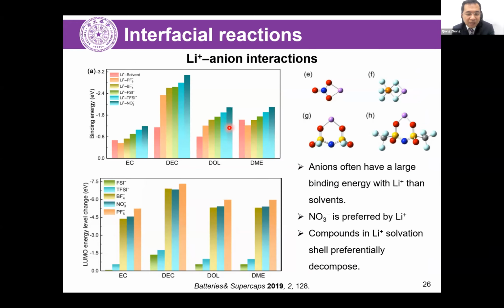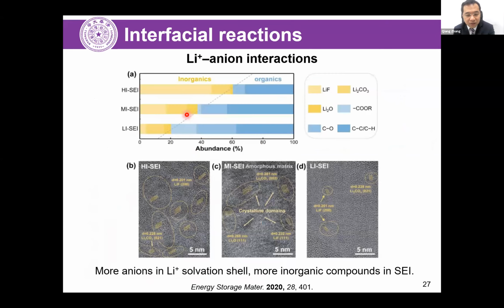So in this case, we use ab initio calculation to probe the bonding energy. And it is found that the lithium-ion solvent complex was quite stable and with strong bonding in EC or DME electrolytes, in which the ion-solvent complex bonding energy was higher than the salt bonding. So in this case, it is found that in some certain systems, the lithium salts prefer to decompose into cations and anions, while the different anions have different bonding energy with lithium ions. For example, the nitrate ions always prefer to have a strong bonding, so they prefer to interlink with the lithium ion in working electrolytes. Based on this consideration, we try to characterize the solid products on the surface.